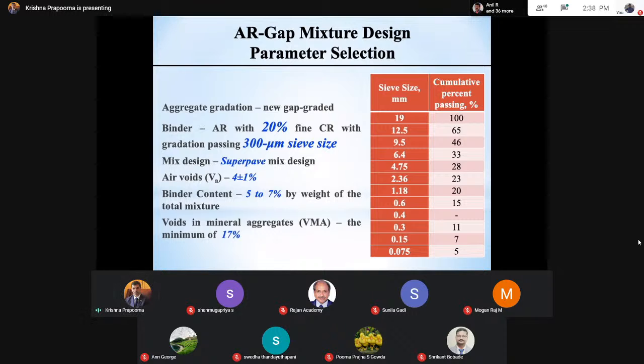Impossible, right? So you take a sample and then you measure the air voids. That's all we do in Marshall. What we do in Superpave is we apply a kneading action when you simulate dynamic loads, and then you make sure that each and every aggregate particle is coated with asphalt cement, which makes it VMA. That's the volume of the mineral aggregates that are coated effectively with binder. That's what is VB effective.